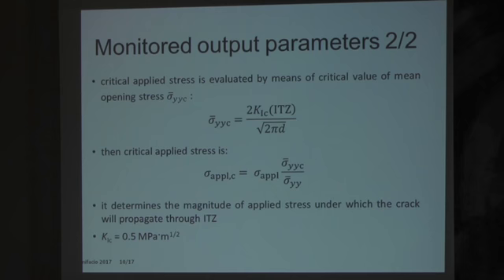For the estimation of this parameter, we considered a fracture toughness of 0.5 megapascal per square root meter, because this is a typical value of fracture toughness for cement matrix.